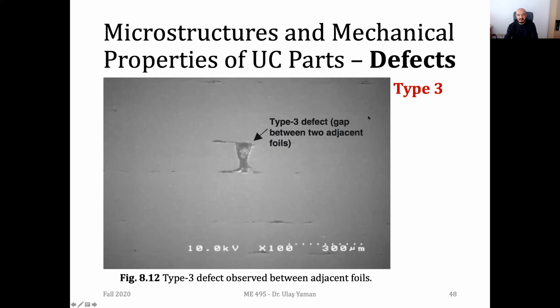And then we have type 3 defect, as I have drawn. This is a top surface of the part. We have some foils actually deposited on the same layer, and as you see, this one is a bit shorter, and we have some gaps in between. They are all type 3 defects. The gap we have between adjacent foils.